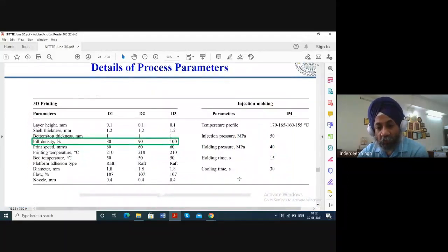And as I told you, we can only compare at the optimized set of processing parameters. So in one of the earlier studies we published, we optimized all these parameters. And finally, in this study, we only focused on fill density of 80%, 90%, and 100%. All other parameters were kept constant. There was no change in any other parameters. All this optimization of the parameters was published in another article. But here, for comparison purposes, the optimized set of parameters was used. Only we changed the fill density just to see how it affects the mechanical performance.